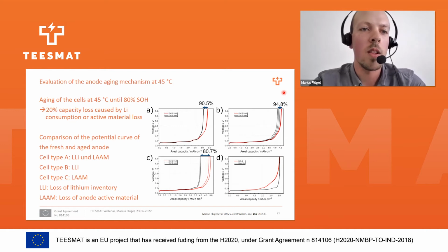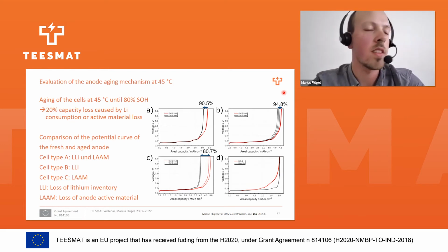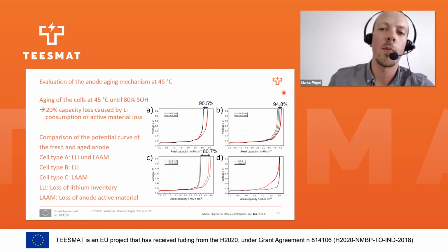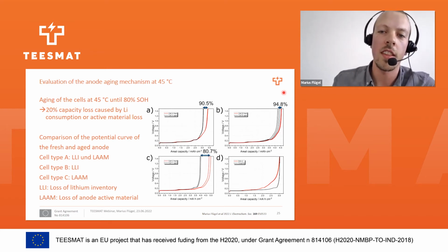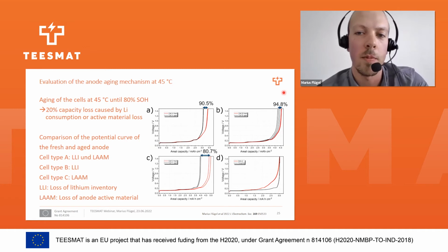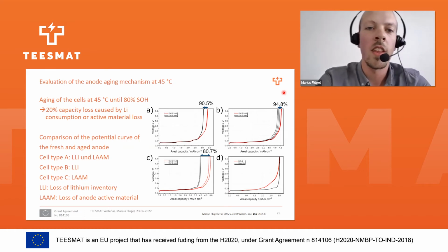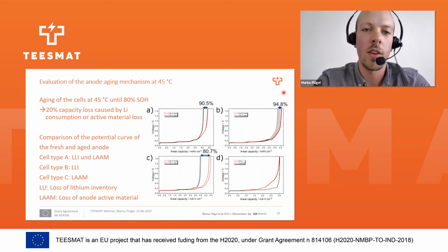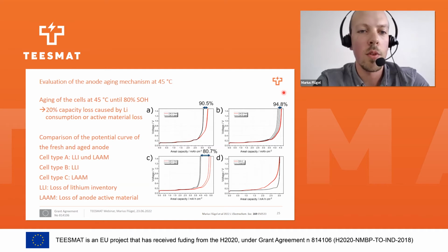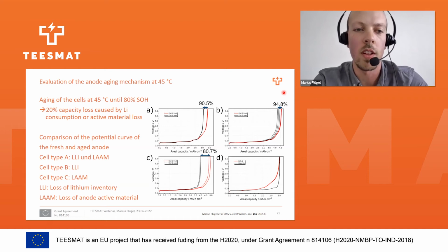To give you an example how we use GD-OES together with different complementary methods, I'm going to present you our recent research. For this, we bought 3 18650 cells, which all contained silicon in the anode. Those cells were then aged at 45 degrees Celsius until the SOH was 80%. So we lost 20% of capacity, either by lithium consumption or by loss of active material.